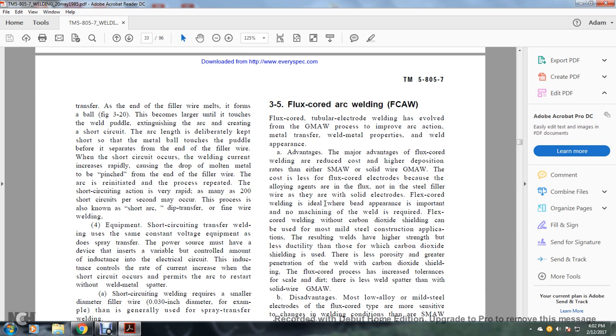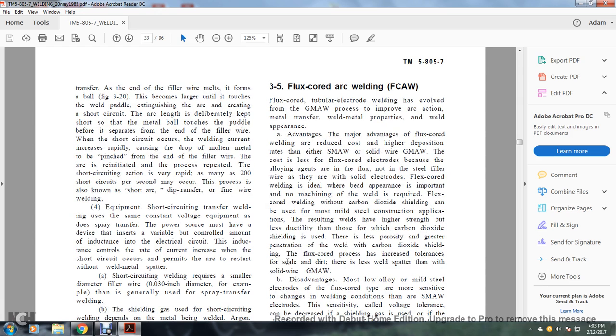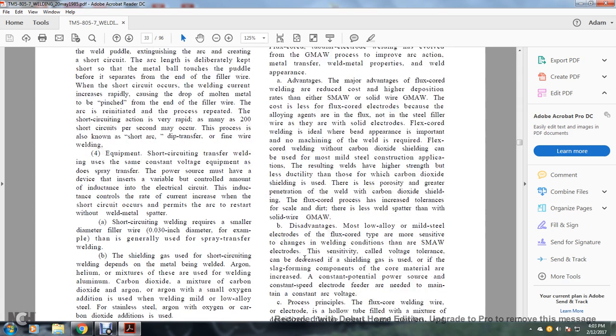Flux core welding is ideal where a good bead appearance is important. No machining of the weld is required. Flux core welding without carbon dioxide shield can be used for most mild steel construction applications, resulting in welds with higher strength and less ductility than those made with carbon dioxide shield. Where carbon dioxide shielding is used, there is less porosity and greater penetration of the weld. The flux core process has increased tolerance for scale and dirt. There is also less weld spatter than with solid wire gas metal arc welding.